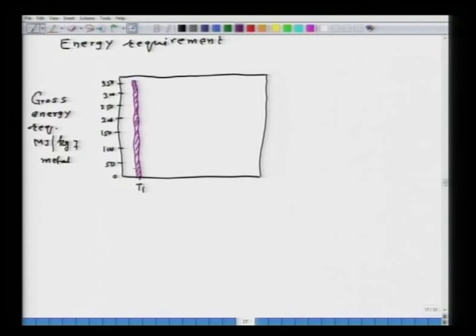Now, on the other hand, if I take, say, aluminium, that would be requiring approximately 200 megajoule per kg of metal. You can imagine the amount of energy that would be required. For nickel, it will be somewhere around, say, 150. This is nickel when we go for the pyrometallurgical route, the pyromet route. Now, if you go for the hydromet route, then slightly higher energy is required. This is for nickel, hydromet route.